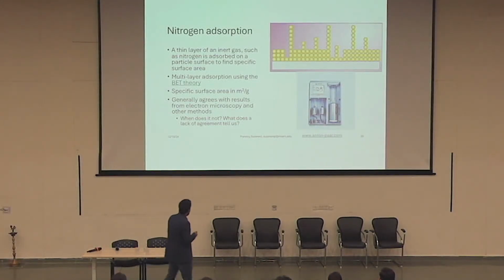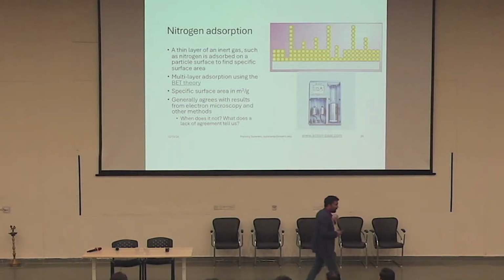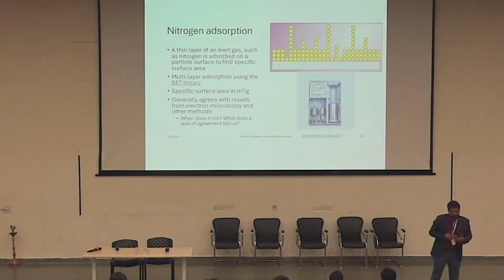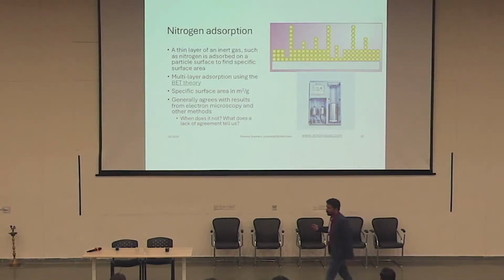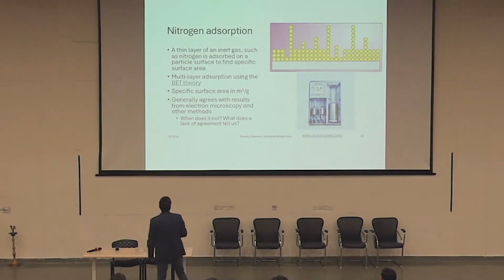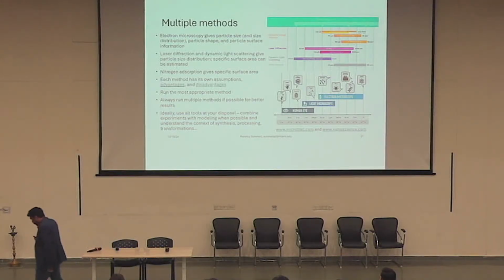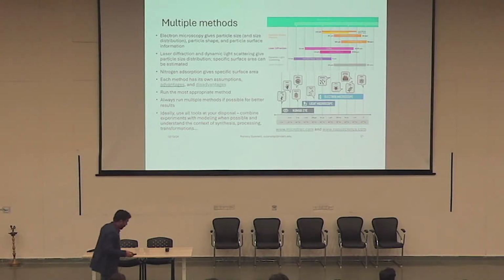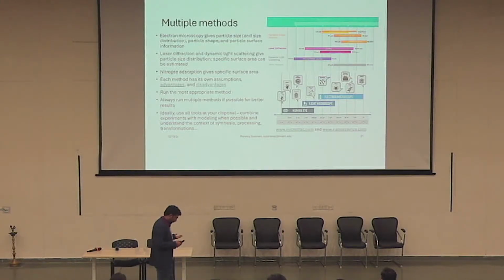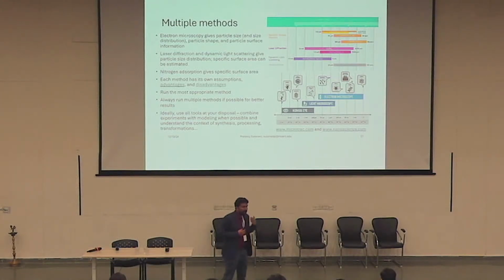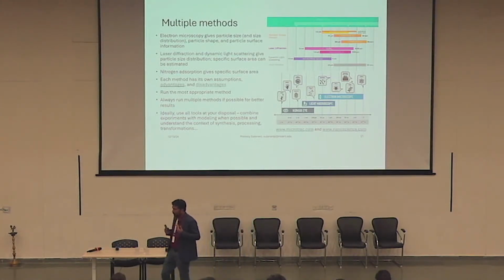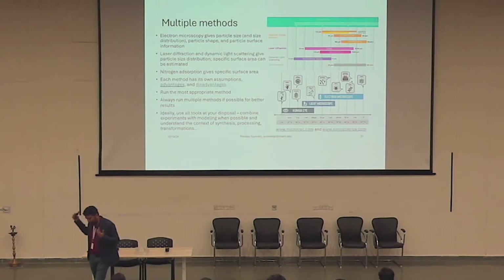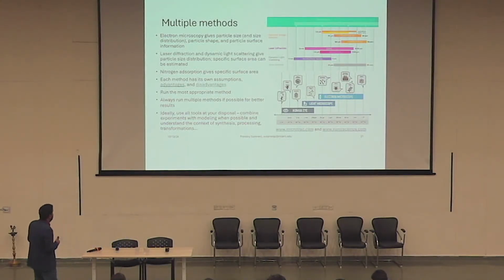And we've already discussed when it does not agree with other measurements, as an example, electron microscopy measurements or laser diffraction measurements, what this tells you about particle shape, size, texture, etc. Multiple methods. So it's important to run multiple methods. Each of these methods is telling you something, and if you put all of them together, the sum is better than the parts, assuming you've used these methods appropriately. Each method has its own assumptions, advantages, and disadvantages. And if you're really caring about measurement, you will know to a certain extent what these advantages, disadvantages, assumptions are. So you can use these methods appropriately.